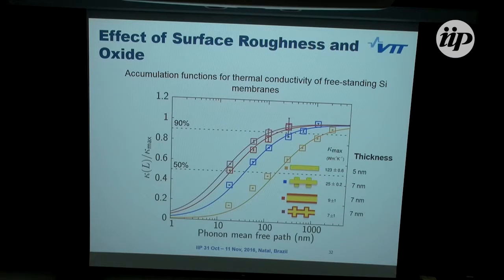This Davide didn't show, but this is also an interesting graph. This is the accumulation function in these freestanding membranes for the same set of samples, and this is the thickness of these model samples. If one takes again this most realistic case, then it is this curve, and this shows that 90% of the heat conducted in the membrane is by phonons with a mean free path less than 100 nanometers. So this gives a feeling, as pointed out earlier, of the size or dimension scale if one really wants to start to modulate the lateral movement of phonons by some, let's say, phononic lattices and so forth. But I think Livia is going to say something about this tomorrow.